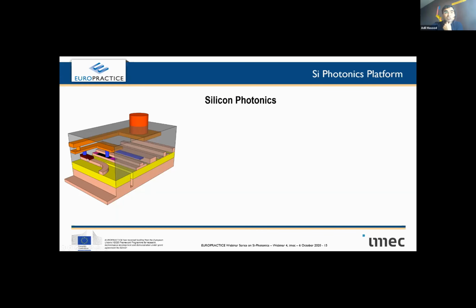Germanium can also be grown epitaxially, which means that where silicon fails in capturing light, germanium can absorb it and act as a modulator or as a photodetector. So there you have things which are not transparent to light, grown on silicon and acting as an additional feature.